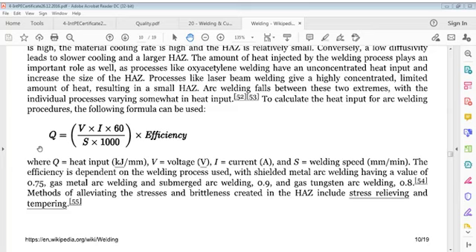To calculate heat input for arc welding procedure, following formula can be used. Q is heat input in kJ per mm, V is voltage, I is current, and S is welding speed in mm per minute. Here Q is equal to V I into 60 over S into 1000 into efficiency. The 60 means you are taking it in minutes, and S is welding speed in mm per minute. Efficiency is dependent on welding process used, with shielded metal arc welding having a value of 0.75, gas metal arc welding and submerged arc welding 0.9, and gas tungsten arc welding 0.8. Methods of alleviating stresses and brittleness created in HAZ include stress relieving and tempering.